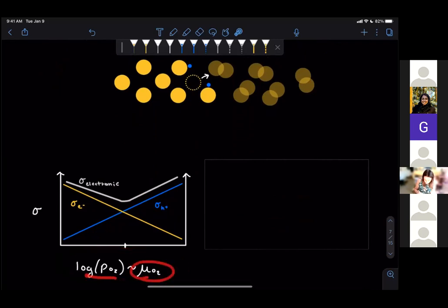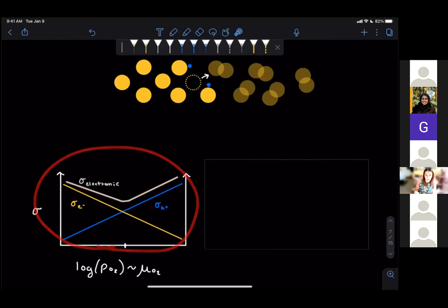And so what that looks like is you have on the x-axis the chemical potential of oxygen, which is related to the natural log of PO2, and some sort of conductivity. So the total electronic conductivity, depending on what potentials we're going through as we're charging and discharging a given cell, dependent on the partial pressures of oxygen in each of the electrodes, could actually reach a place where there's a local minimum. The data I'm showing here comes from things that have been measured for YSZ electrolytes, so this is a phenomenon that does indeed occur.